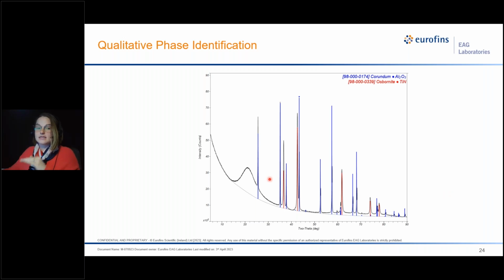And because these have different crystal structures, the diffraction peaks will show up at different points in 2 theta. So we use XRD like a fingerprinting technique. If we know some of the elements in the sample, we can restrict the database search by those elements, so it's not searching all 500,000 compounds in this database. And something important to remember is that XRD is structural, it is not elemental. So if you have 2 compounds that have the exact same structure, but the atoms in the structure are different elements, the peaks will show up in the same spot because it actually can't see what element it is.